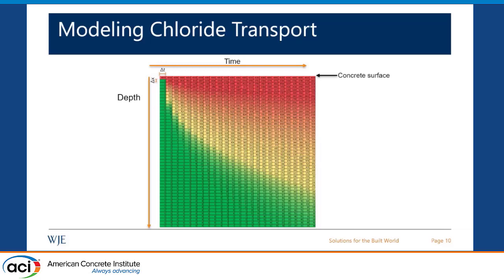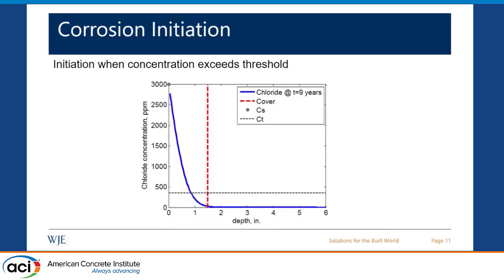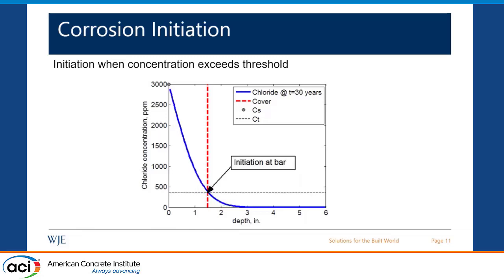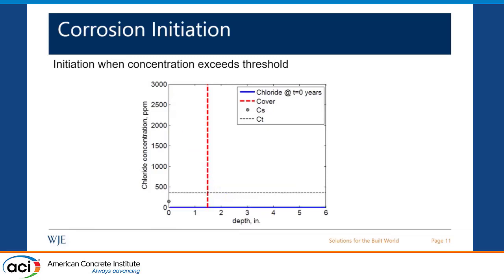But here we have full control over the process. We do the discretization with depth of the concrete and also with time, but we have full control to decide what delta X and delta T to use. That gives us the capability to model even shallow cover, which is the discussion we had earlier here. At each time step, we look at the chloride profile and how that changes with time, and we define the initiation time as the time when the chloride concentration at the depth of the bar exceeds the critical concentration, which we call the chloride threshold.